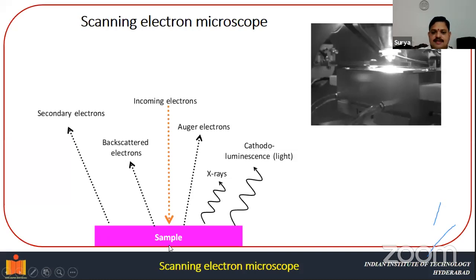Now, the thing is that from the sample, there will be many outputs, like secondary electrons, backscattered electrons, Auger electrons, X-rays, cathodoluminescence light. All these things will be byproducts as a result of impinging the electrons on top of the sample. It all depends upon what you would like to characterize from the material. For instance, if I want to know information about the morphology of the sample, you have to detect the secondary electrons. You put a secondary electron detector at an appropriate angle, and you can detect the secondary electrons.